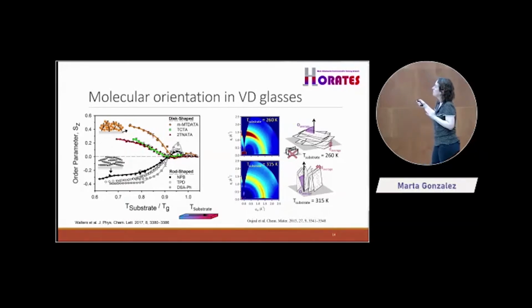However, if you prepare them by depositing, by vapor deposition, depending on the temperature range of deposition, here it's normalized to Tg, okay, but this is changing the temperature of the substrate. Depending on the temperature, we will have some order, but it's not exactly an order. It's more like a tendency to, for instance, the molecules get parallel to the substrate. So at a certain point, it's a certain degree of order, but you don't have correlations, okay? So we have the tendency to get our molecules more or less flat, only if the substrate temperature is low enough, because we are not providing time enough and temperature enough to equilibrate.